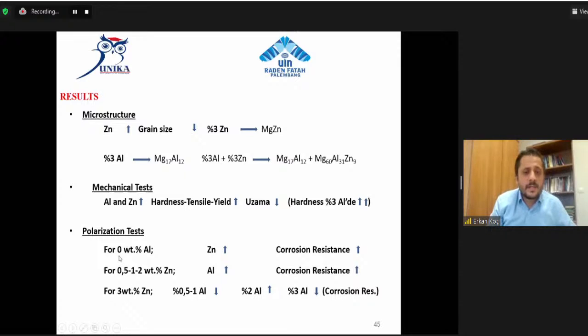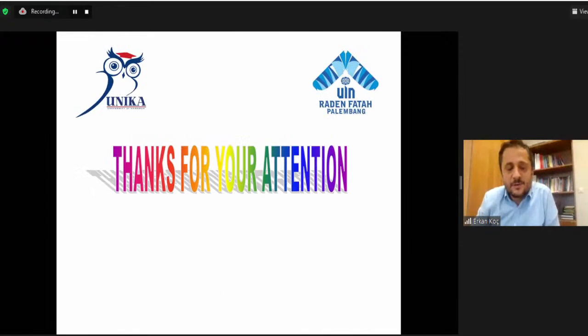For the polarization test, for 0 aluminum, when the zinc increases, corrosion resistance increased. But if you use 0.5, 1 and 2 weight% aluminum, corrosion resistance increased. But when the alloying elements are increased, for example, 3 weight% zinc and 0.5 and 1 aluminum, corrosion resistance decreased, and with 2 aluminum it increased, but 3 aluminum decreased because of the intermetallic phases. Thanks for your attention. Thanks for listening to me. It's okay now, I finish my presentation.